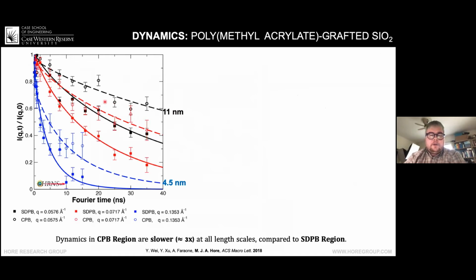And what you can observe is that no matter which length scale we're looking at, the dashed line is always quite distinct from the solid line. That's true in the red and that's true in the blue. So we're looking at relaxation times over length scales of 11 nanometers here to relaxation times over length scales of 4.5 nanometers. So we're going from relatively big relaxation, or the relaxation times of relatively big regions, to the relaxation times of very local regions here. So we're going from large scales to smaller scales.